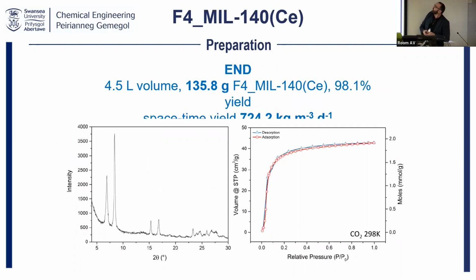So we ended up with a synthesis of 140 grams, from 200 milligrams. You might recall that the other one looks like this, so we are making exactly the same material. We scaled up the right thing. And again, the absorption properties of this material are pretty much similar, just the capture dropped a bit, because when you scale up, some factors are not as good as in the small size. So this is just to tell you that, especially for the UKCCSRC, we did what we were supposed to do.